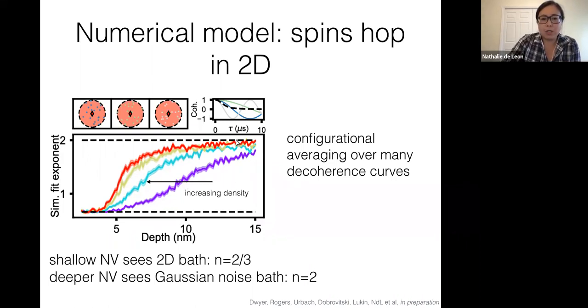And indeed, if you just do this configurational averaging with straight numerics and Monte Carlo simulations, then what we see is that for very deep NV centers, you'll fit to an exponent that is 2. So it gives you the good naive model. But for very shallow NV centers, this configurationally averaged two-dimensional bath actually should give you an n of 2/3. There's a term in the theory that gives you something that looks like d over 3. So for shallow NVs, we get n of 2/3. For deep NVs, we see n equals 2.